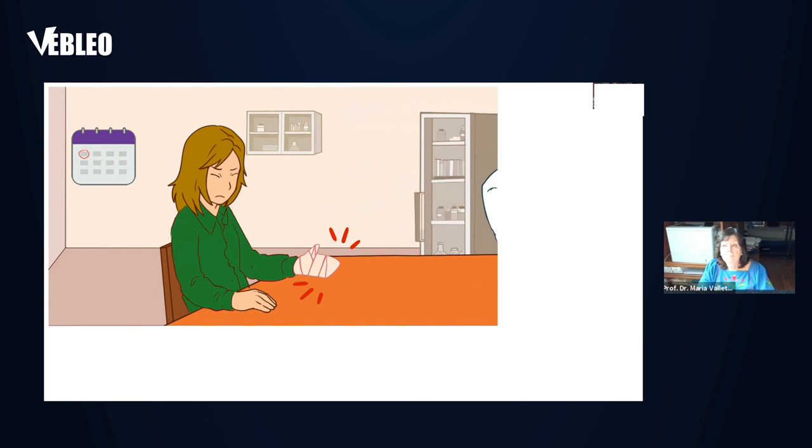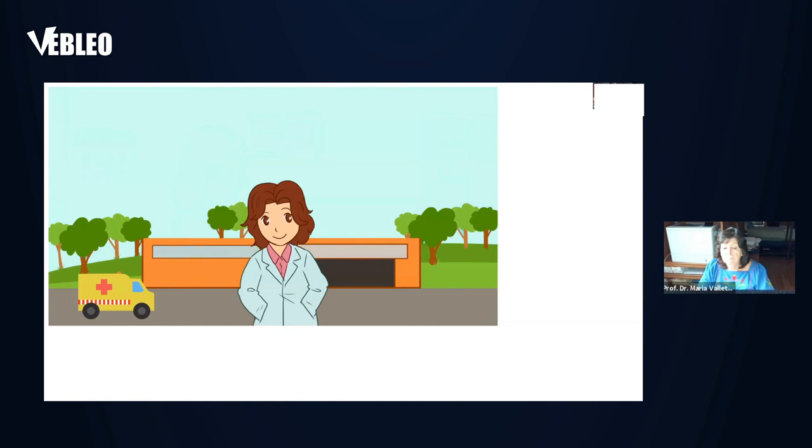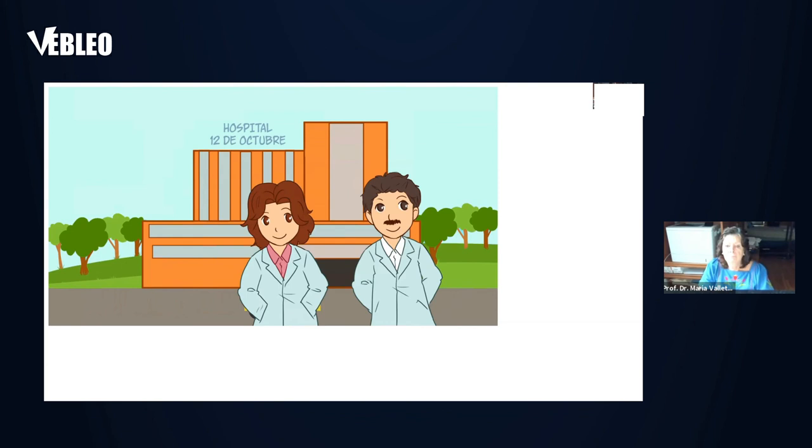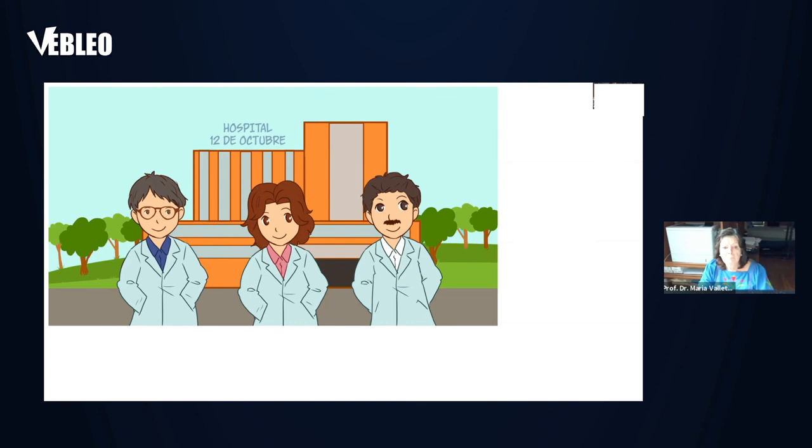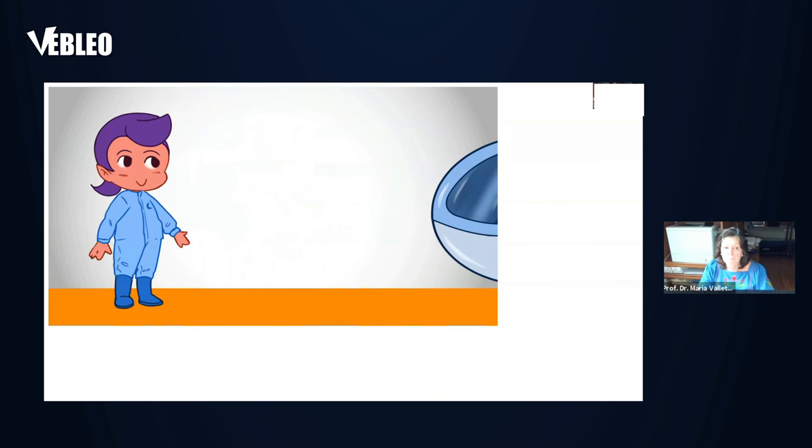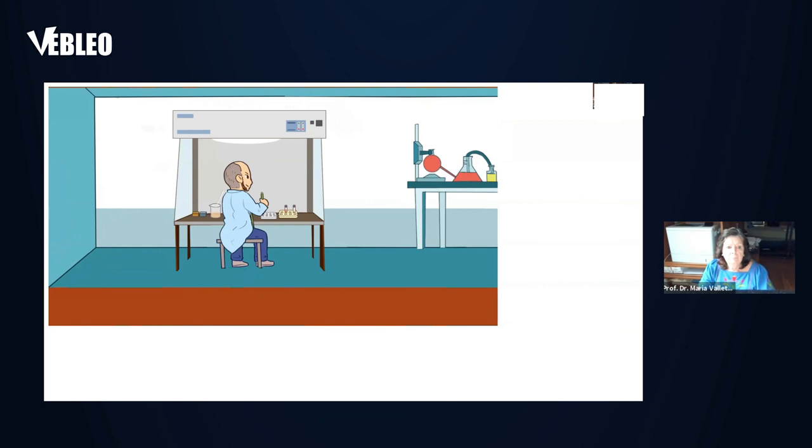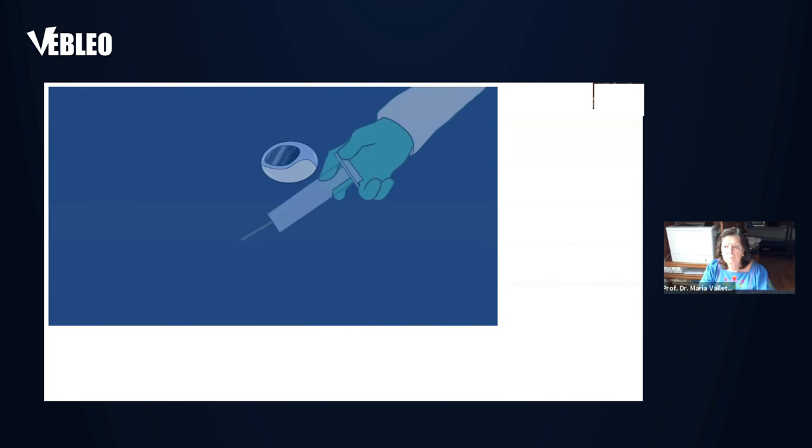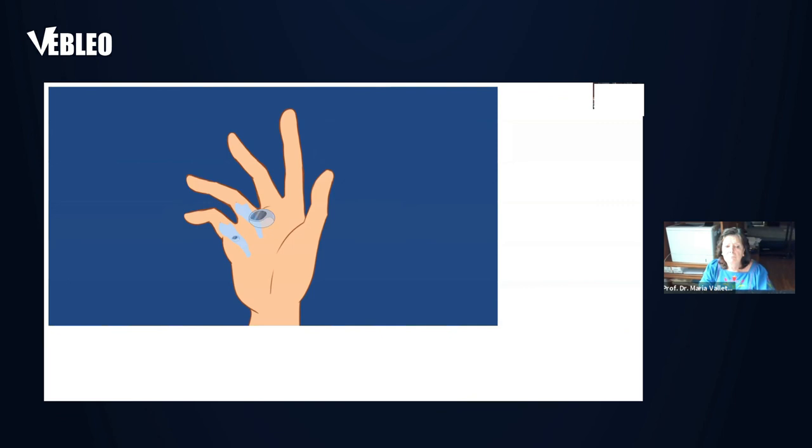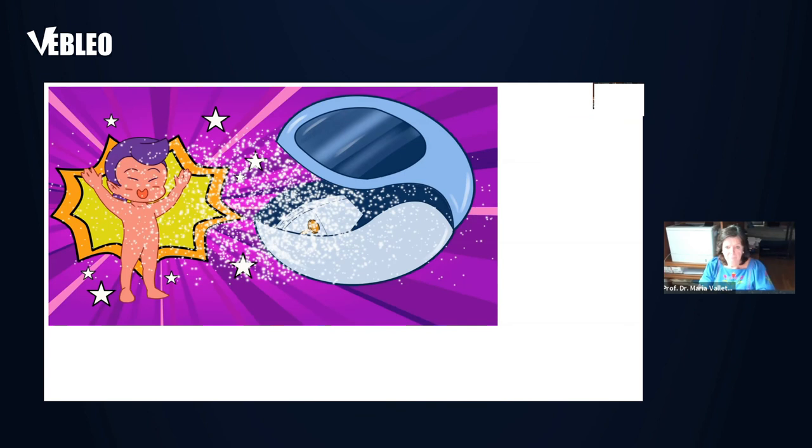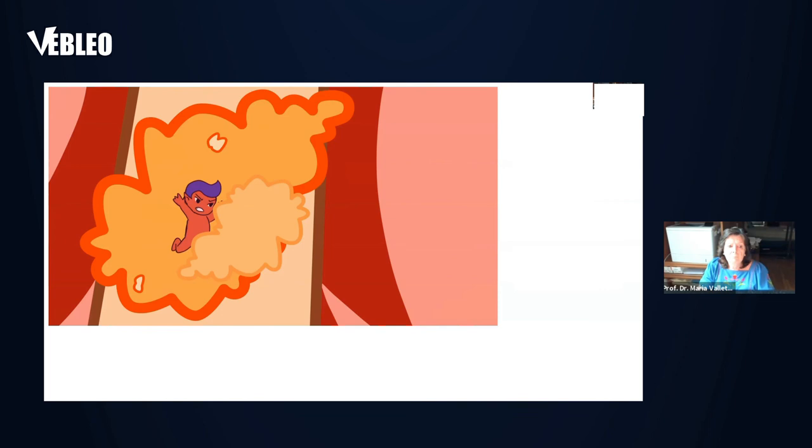Thanks to the collaboration between the research group of Professor Maria Vallet-Regí and that of Drs. Pablo Ortiz and José Luis Pablos of the 12 de Octubre Hospital, a novel methodology for the treatment of fibrosis has been developed. It is based on nanocapsules that protect the collagenase enzyme by covering it with a polymer. The steps of the method are: first, the collagenase nanocapsules are prepared in a personalized way for each patient. They can also be adapted to carry other drugs. Then, the nanocapsules are injected into the fibrotic region, and once in the fibrotic tissue, they are opened when ultraviolet light is applied, and they release the collagenase.